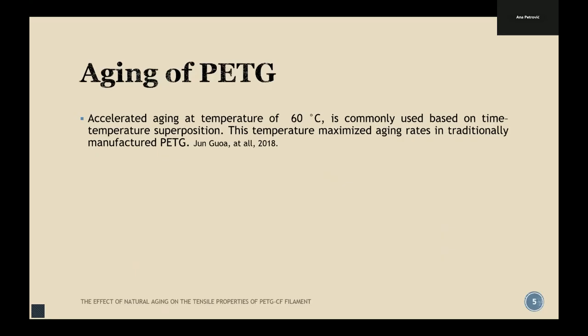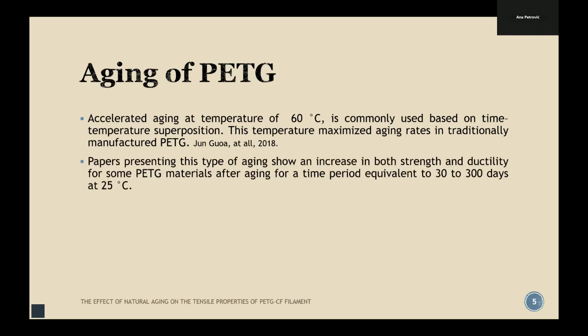Accelerated aging at a temperature of 60 degrees Celsius is commonly used, based on time-temperature superposition. This temperature maximizes aging rates in traditionally manufactured PETG. That's the common sense you can find in many papers, but our opinion is that 60 degrees Celsius is a high temperature for filaments and for polymer materials. So we do not want to do this, and we do natural aging instead.